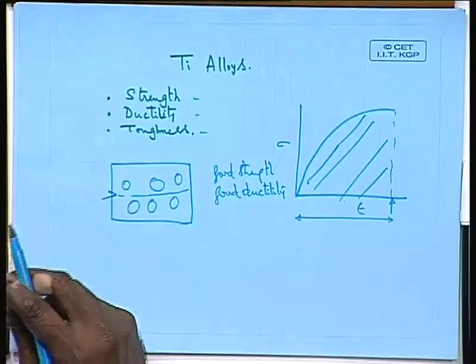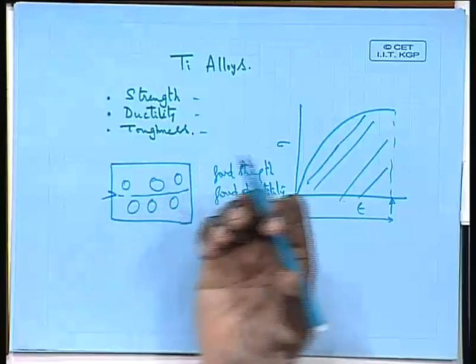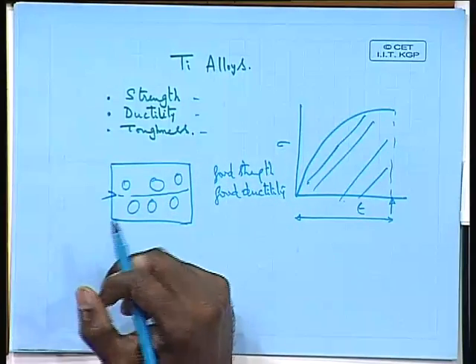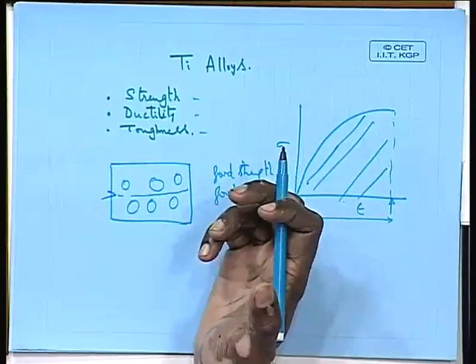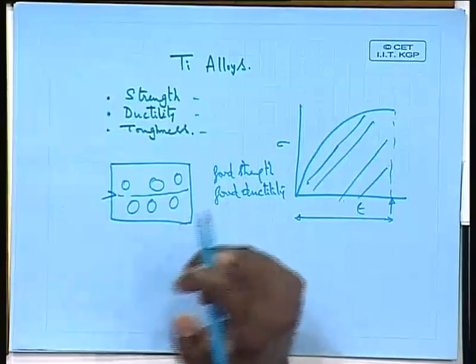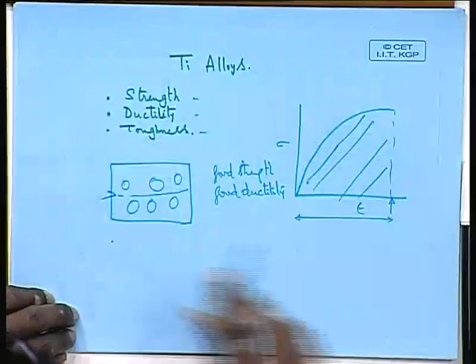Basically, if a crack is initiated inside the material, let us imagine a crack is initiated here, it can easily propagate because these are all mostly spherical particles. Spherical particles do not really offer much resistance for the crack propagation. But if you have acicular type of particles, particularly which are randomly oriented, that means if you have a microstructure,